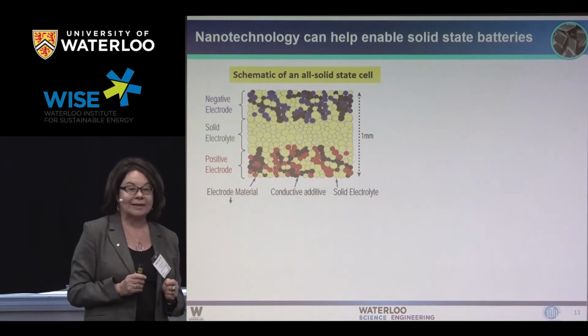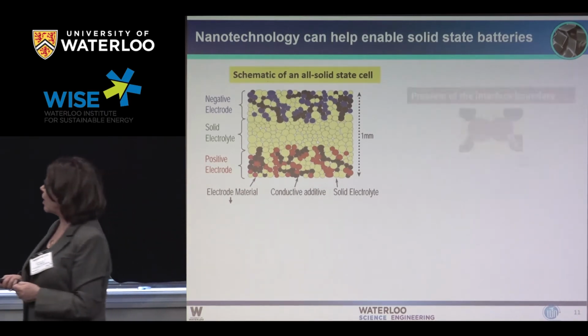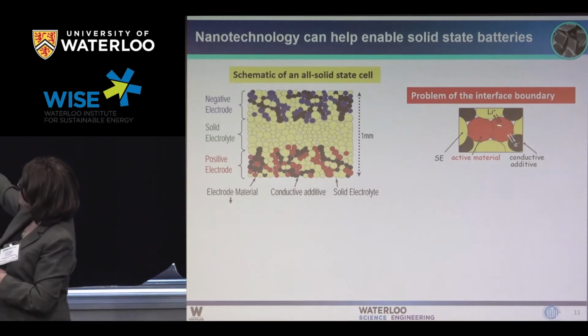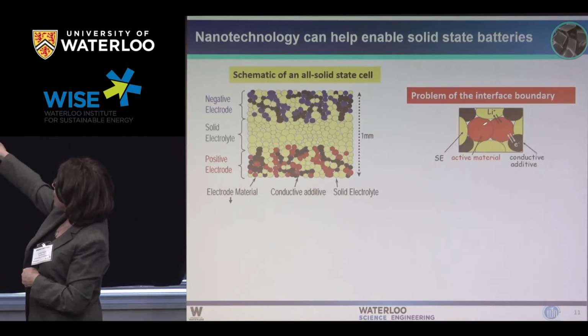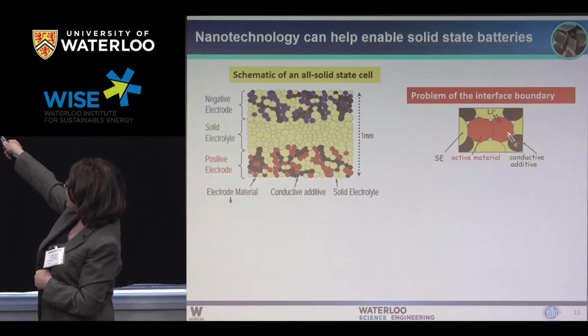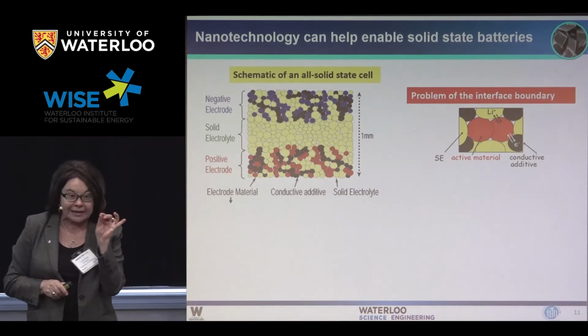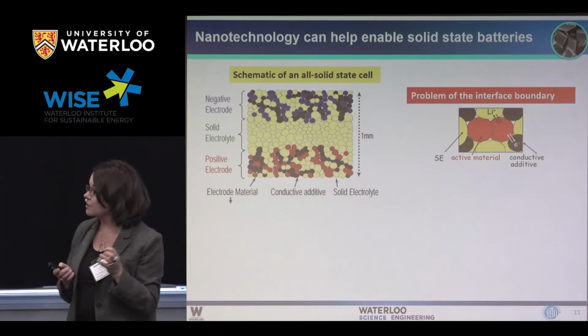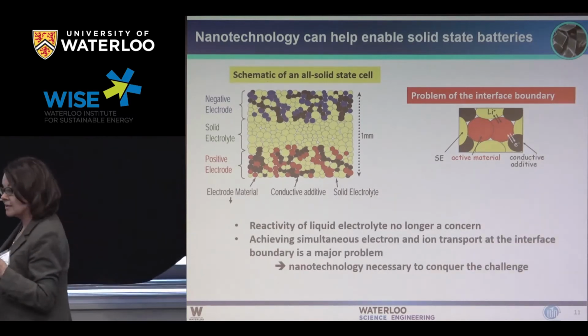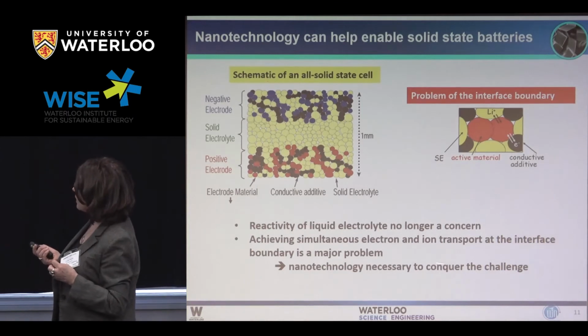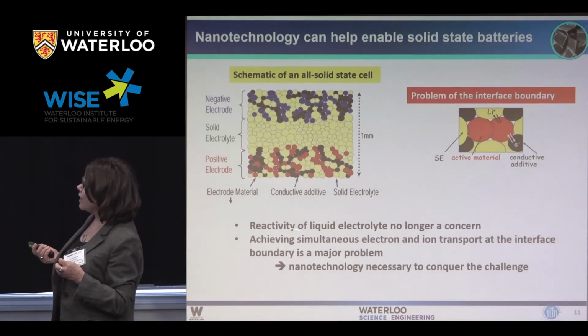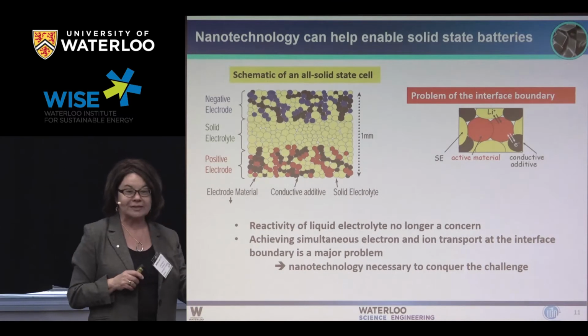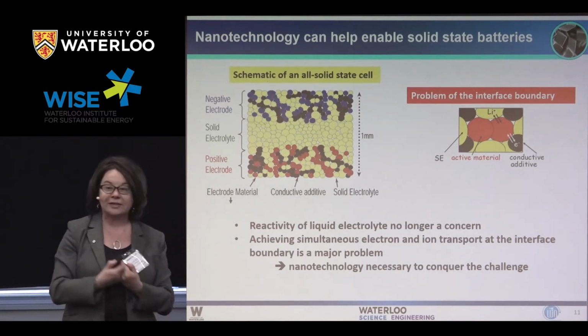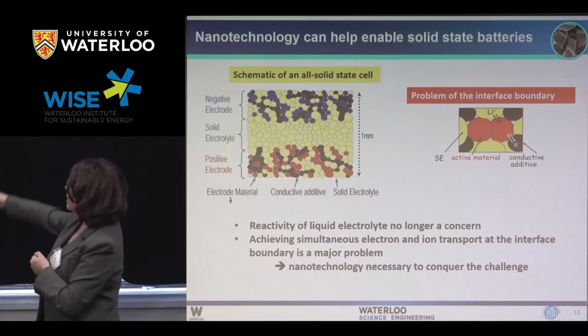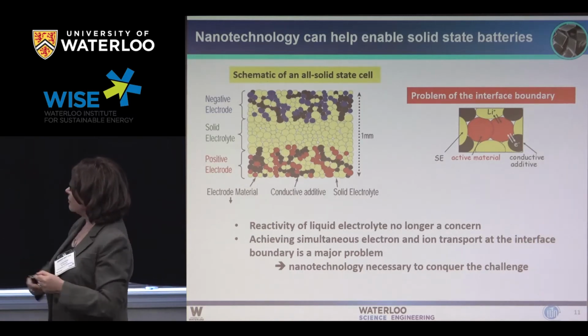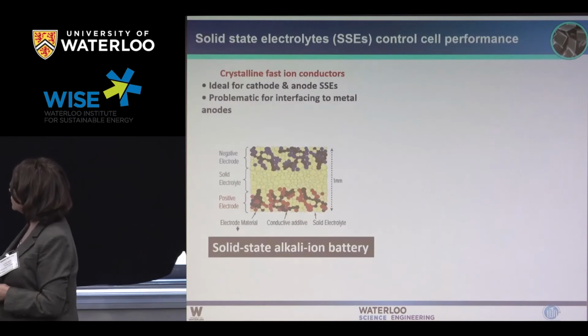How do you mix solids together at that intimate level? That's the big problem. So we have an interface. Here's our, say, our active material here, and we want to be able to transport lithium ions and electrons simultaneously at that interface. So that means those interfaces have to be very, very well mixed. And that's where nanotechnology is really necessary to conquer the challenge. So we don't have the reactivity of the electrolyte at the interfaces. Now we have the problem of getting solid interfaces together and making that path length for transport of both of these carriers fairly small. And so that's the big challenge.